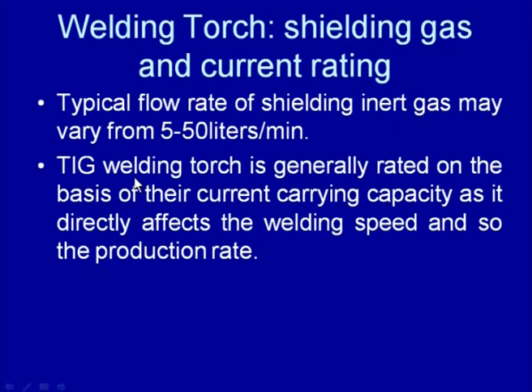The tungsten TIG welding torch is rated on the basis of its current carrying capacity, and this may be 200, maximum 300 amperes. This decides how much maximum current can be obtained from the power source associated with the welding torch, and it directly affects the welding speed, because the higher the welding current we can draw, the more heat can be generated, which in turn will allow a higher speed of melting, and so a higher speed of welding can be obtained, which in turn will help to achieve a higher production rate.